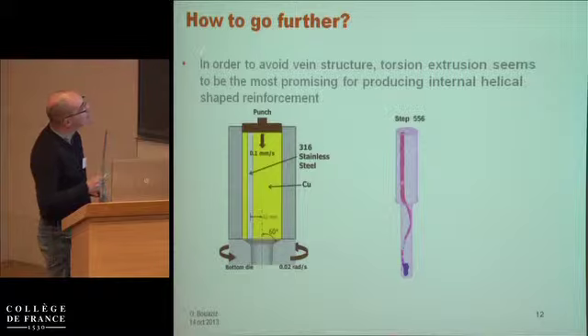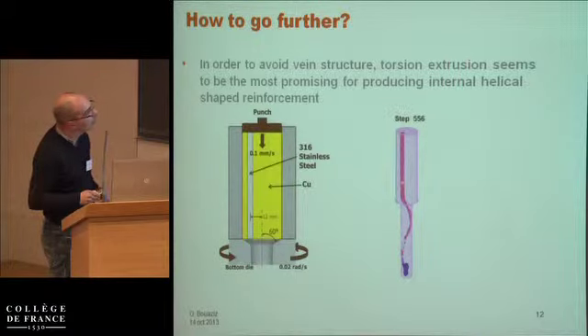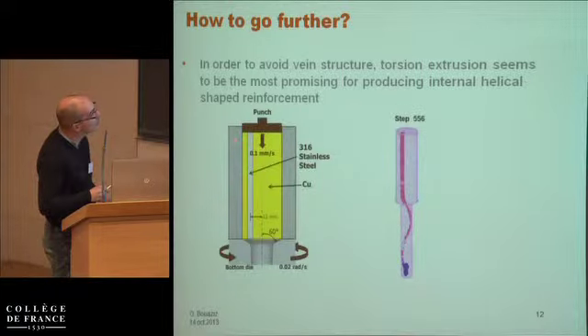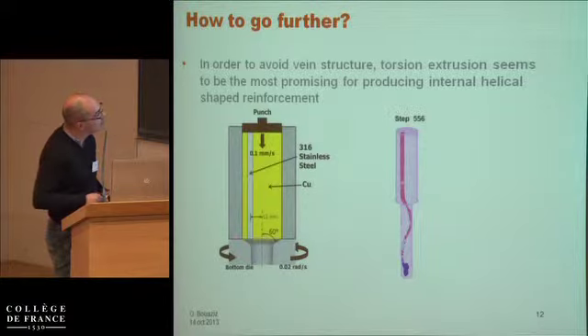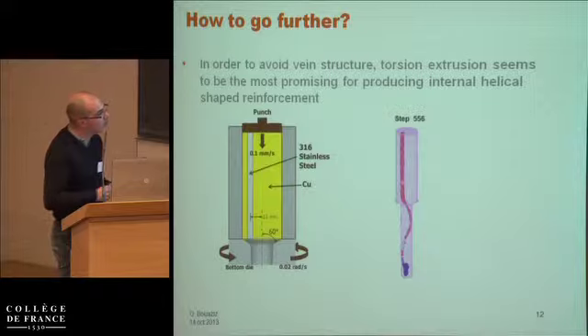So how to go further? In order to avoid vein structure, torsion extrusion seems to be the most promising process for producing internal helical shape reinforcement. So what is torsion extrusion? This is an extrusion die, but suitable to be in rotation in order to induce shear at the same time as the extrusion force. And imagine if you put an insert in the initial sample, you can easily create the internal helical reinforcement, but without the vein structure, so without the pull-out of the material consisting of the insert.